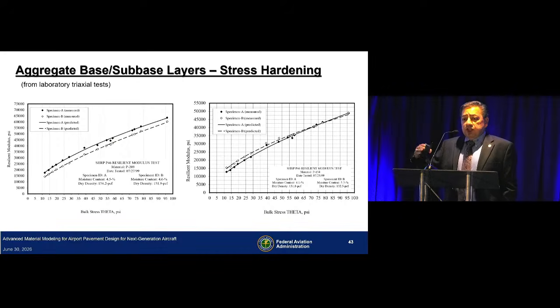So the measurements I showed in the previous slide were in an actual pavement structure. When you test these materials in the laboratory, granular materials are generally tested in a triaxial test, and you apply different combinations of confining stresses and deviator stresses. So what I have shown here are the results for P209 crushed stone base material. And what you can see is the x-axis is the bulk stress theta and the resilient modulus on the y-axis. And you can clearly see as the stress magnitude increases, the stiffness of the material increases. So that's what we call a stress hardening behavior.